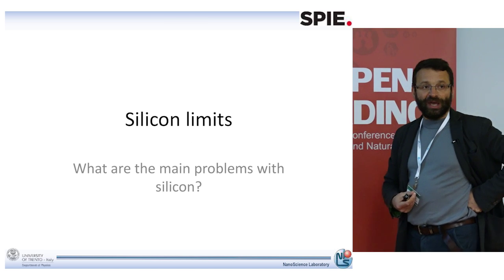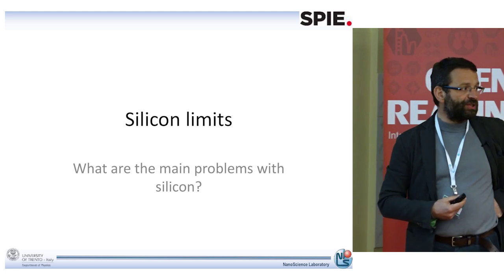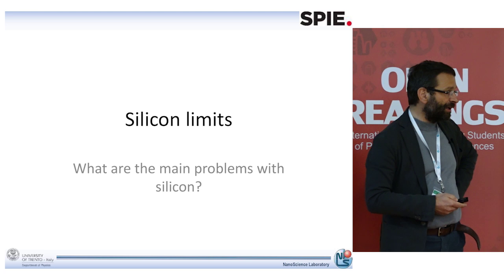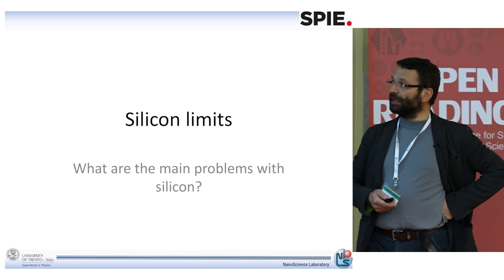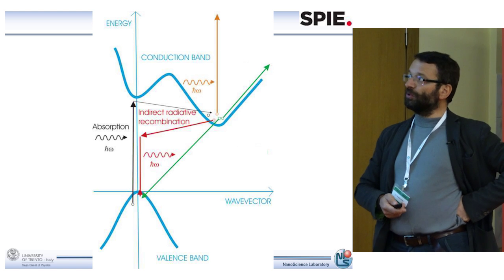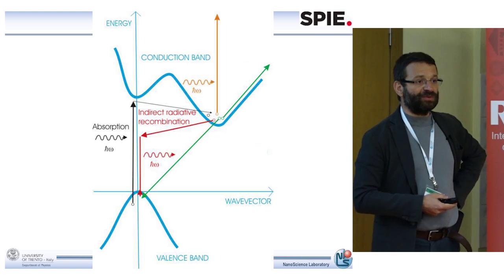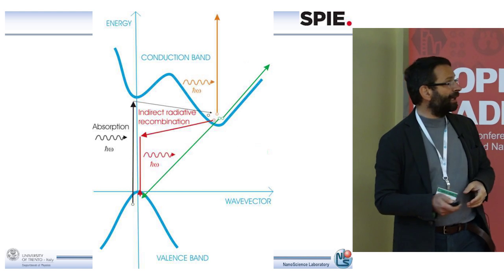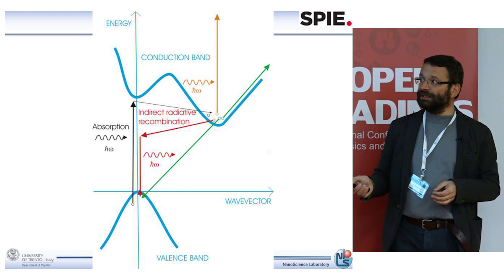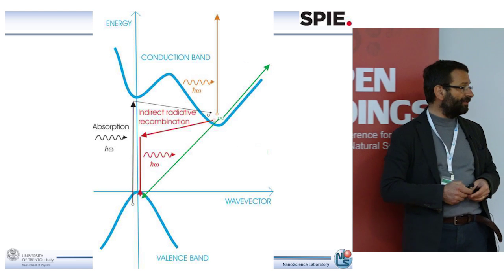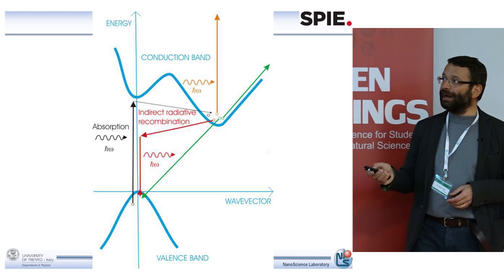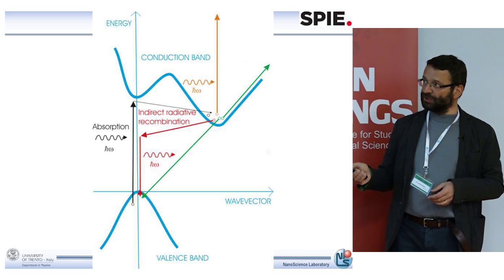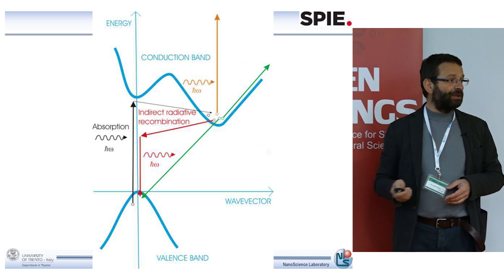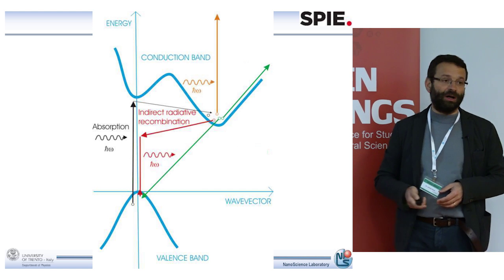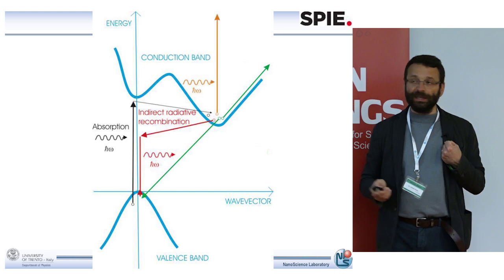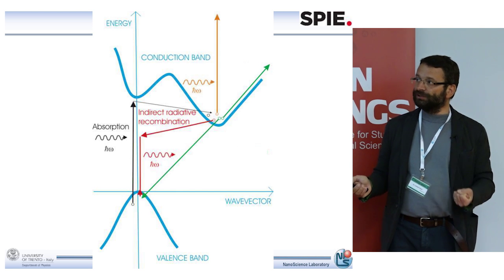Because there is a fundamental limit in silicon, which is associated with the band structure of silicon. This is a textbook graph. We know that silicon is an indirect band gap semiconductor. Indirect band gap semiconductor means that the top of the valence band is not at the same point as the bottom of the conduction band. If you want to move one electron from here to there, you have to conserve the energy as well as the momentum. And in order to conserve the momentum, you need the assistance of a phonon. The phonon has to take the momentum so that you move the electron from here to there.